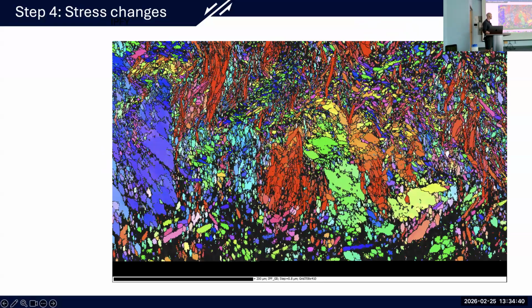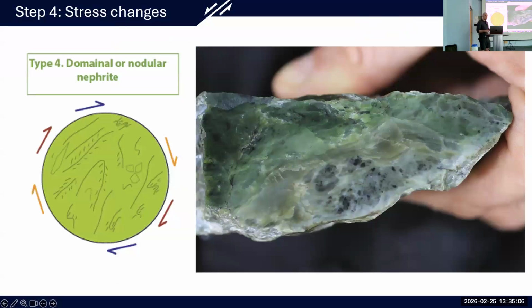mineral fabric. And so here we look at that EBSD map, and we can see that locally, there are domains that are well aligned, but globally, over the scale of, in this case, a 200 micron scale bar, we have such a range of orientations, and it's this range of orientations of these amphibole needles that gives us that incredible strength within the rock. And so this is really the final key, the final piece of the puzzle to developing our nephritic fabric that we saw earlier.